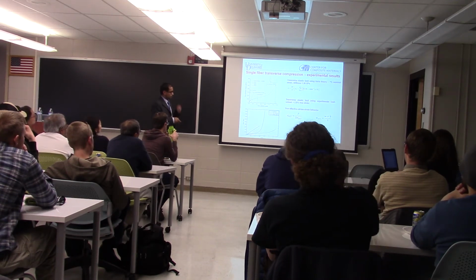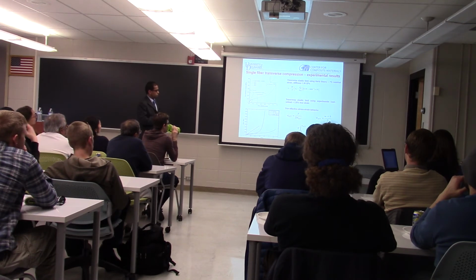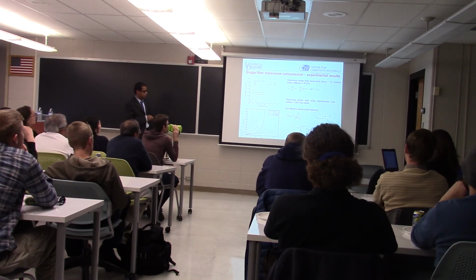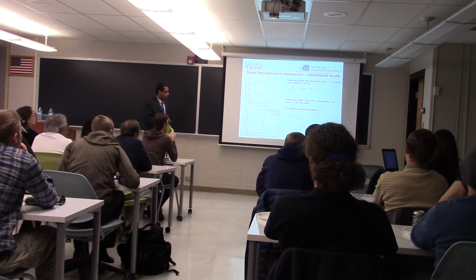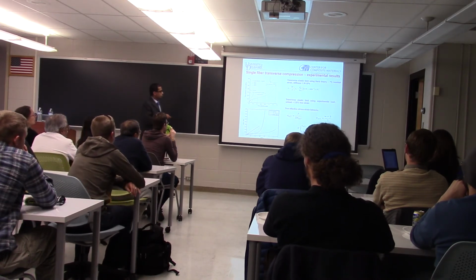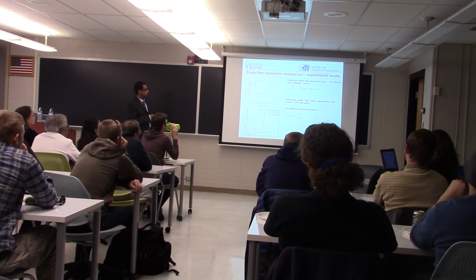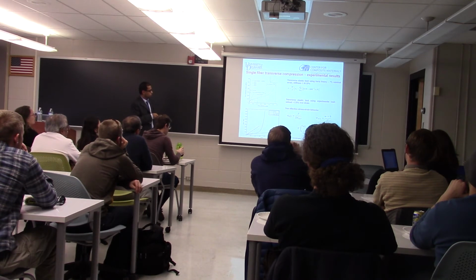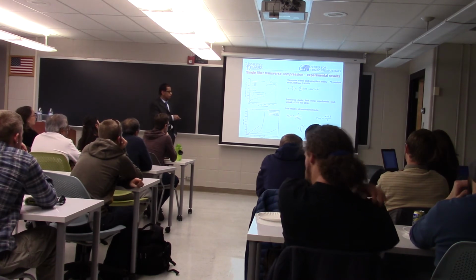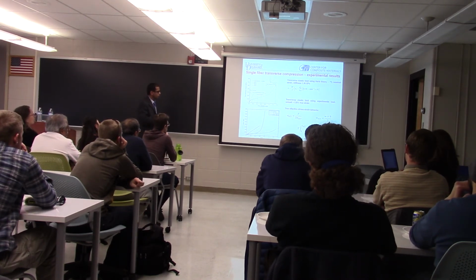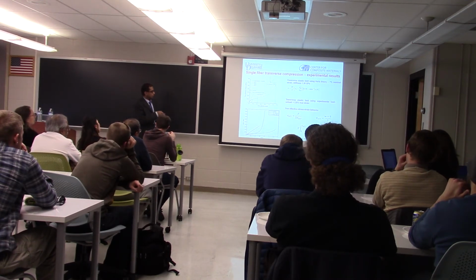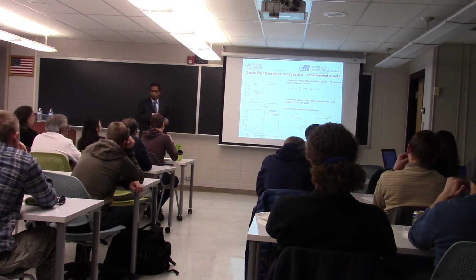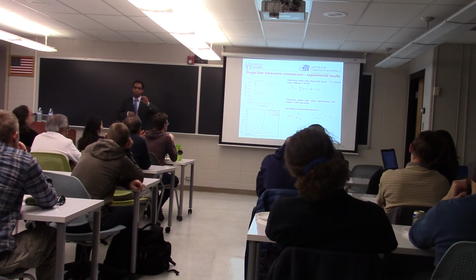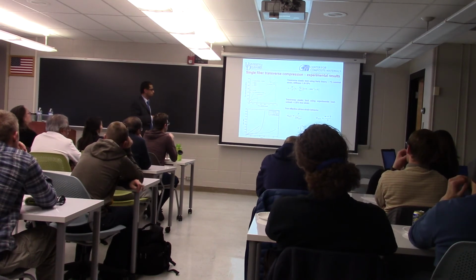So now to obtain true stress-strain behavior, we normalize the applied force by the measured effective contact area, and then the true strains are obtained by equating the internal energy to the external work done. By this we are able to get the true stress-strain response of these fibers. The response can be categorized into 3 zones. We have a very small linear elastic zone. These fibers have a very small elastic limit, only just over 1%. The second zone is where the fibers soften and also the fibrillation initiates. And the third zone is where it shows a stiffening behavior because now the width growth has plateaued. And we think that the fibrils are being compressed in this third zone.